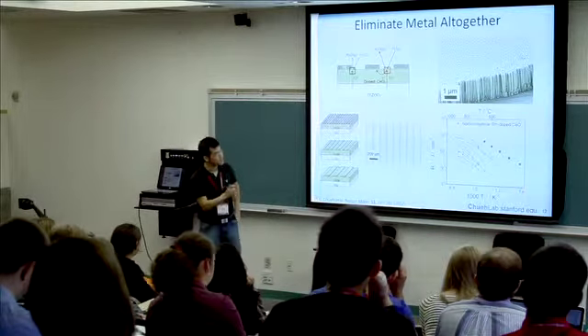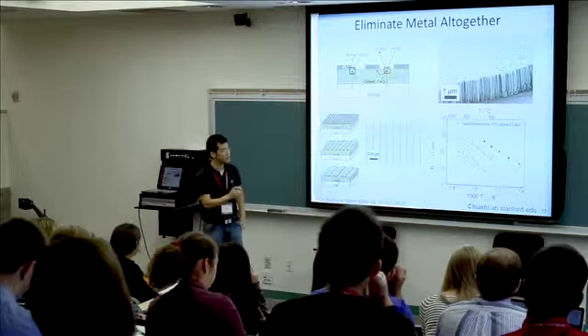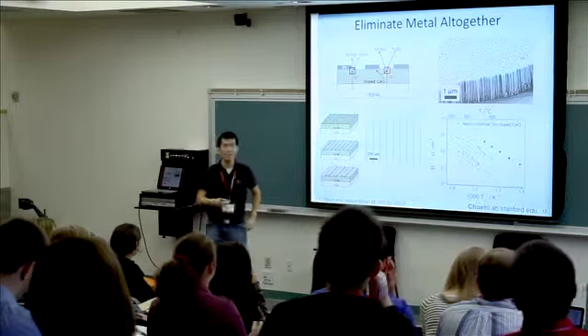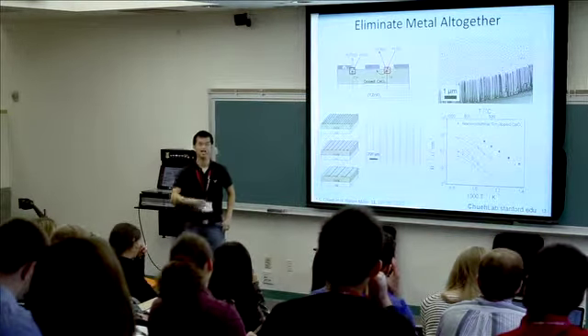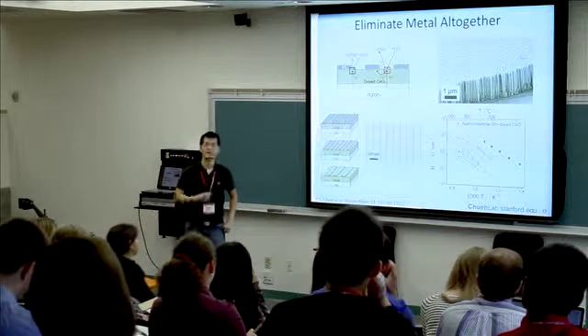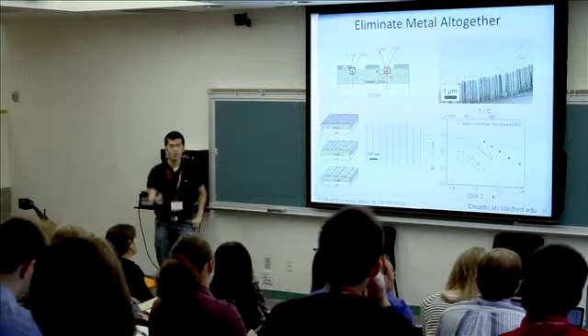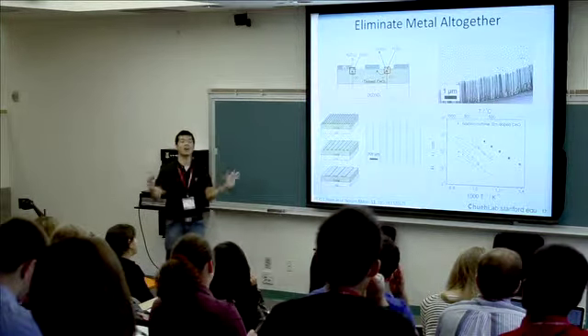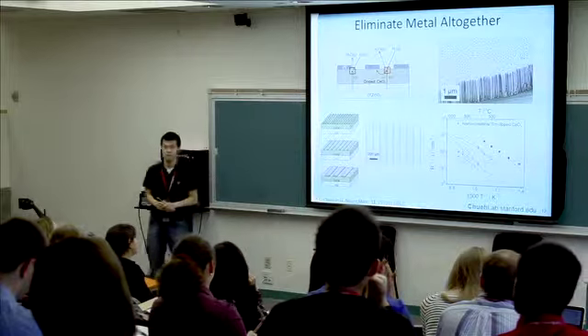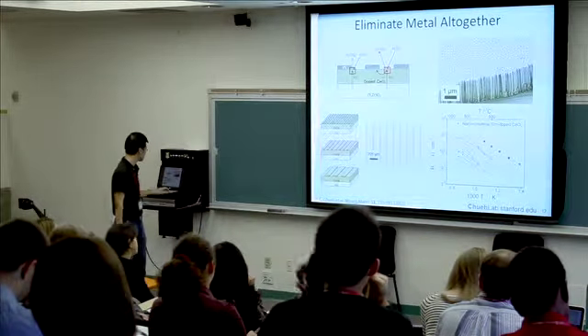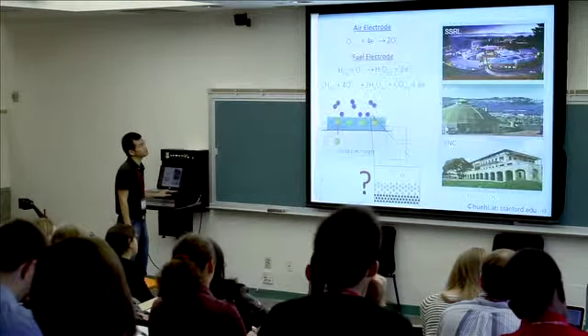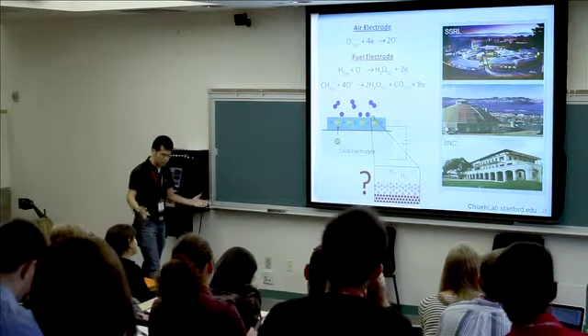In red is what we call the nanocolumnar cerium oxide. It's actually better than any of the other catalysts which have nanostructured materials like platinum, nickel, ruthenium, rhodium, and so forth. So even without any metal, it's one order of magnitude better. This really, again, shows the importance and the benefit of going to high temperature. But, of course, we're not stopping here.